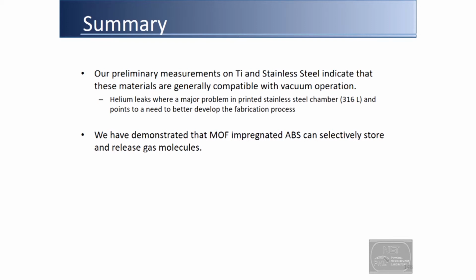One of our results so far is, just like others have found, that titanium and stainless steel are generally speaking compatible with vacuum operations. One of the things we have found is titanium was fantastic for vacuum operations. We had no problems getting chambers printed. But we had some issues with the stainless steel. Our record was about a 33% success rate in not getting helium leaks.